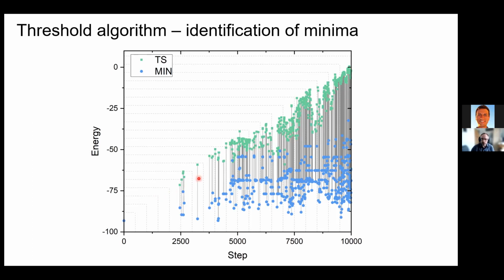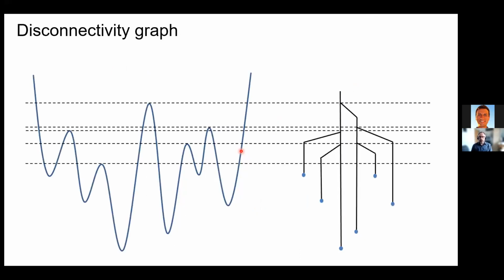And these green points are where we get to in terms of energies, what gets accepted. That keeps creeping up and up and up. And the blue points are currently what we have to do to identify what minimum we're sitting in, which is to locally energy minimize either all of these structures or at increments along our trajectory. We energy minimize structures to see what local minimum we're sitting in, and that allows us to identify when we have those connections.